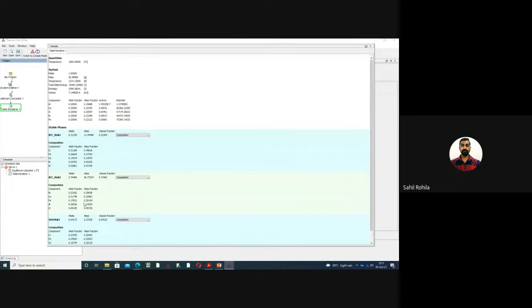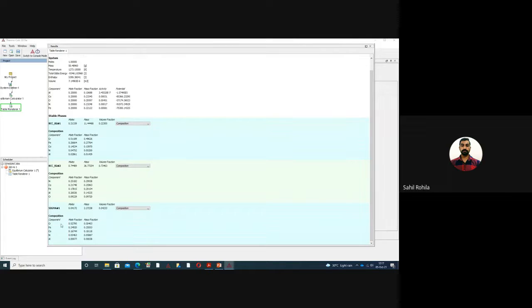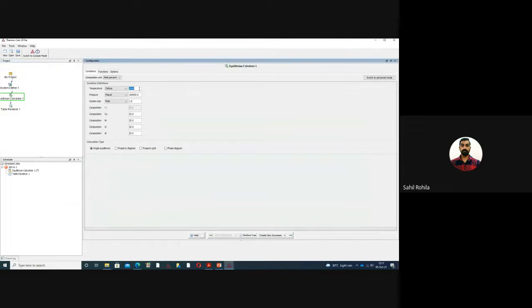So if we have any other temperature, here we can select the quenching temperature, or if we want our alloy to perform at such and such temperature, before making that alloy we can get to know that yes, a sigma phase is also present. So if we change our temperature from 1000 degrees centigrade to, let's say, 1200 degrees centigrade, will the sigma phase be there or not?